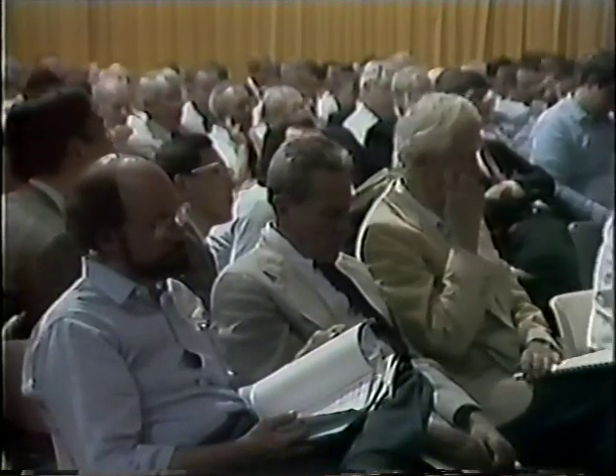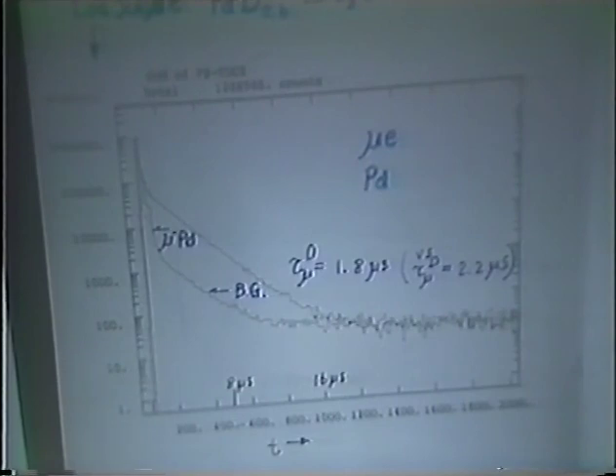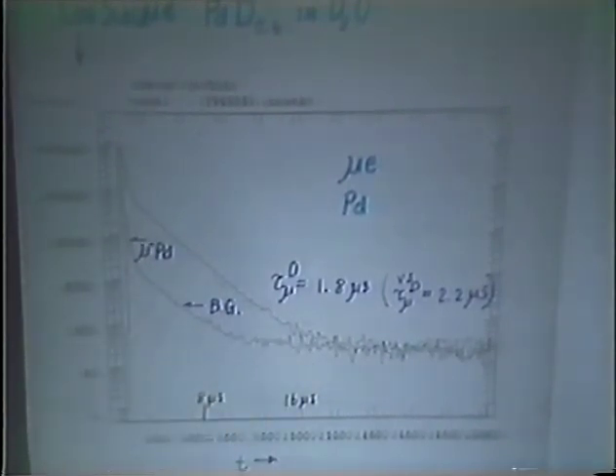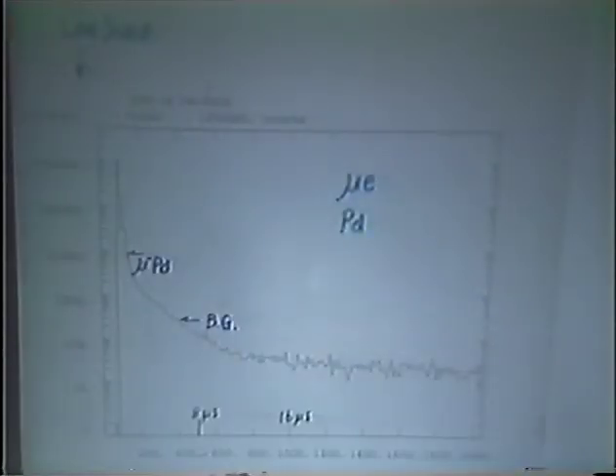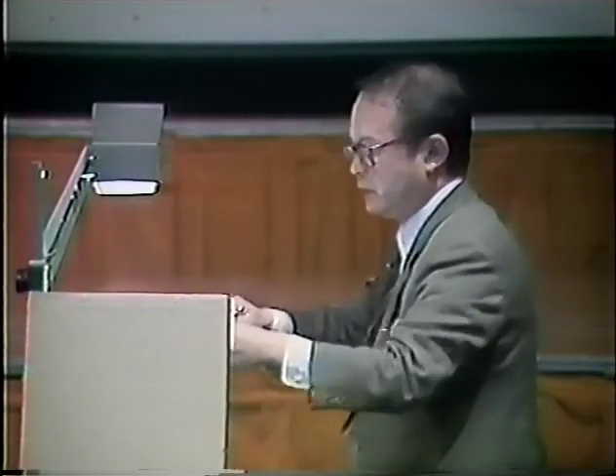And when we install the palladium deuterium system in D2O, there is a significant difference. A long component appeared, but unfortunately this is not muon captured to palladium, and this is not muon captured to deuterium. After the analysis, the lifetime of this component is found to be 1.8 microseconds, not 2.2 microseconds. In order to show you the result more clearly, this is a summary.